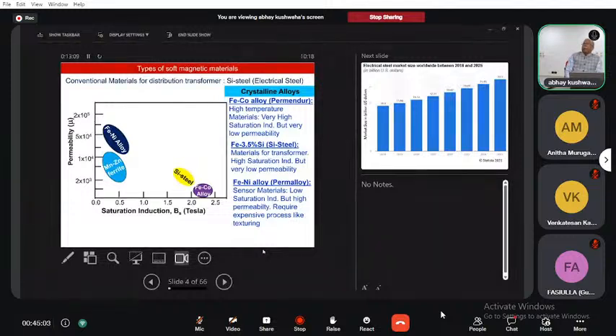But the process of making is just like a steel: melting, casting, rolling. This silicon steel is also made in the same fashion. So that is why it is called the silicon steel. And you can see in the graph where we have put saturation magnetization versus permeability. Our major goal for development of magnetic materials is how we can go higher and higher in saturation magnetization, and for the same material, how much higher we can go in permeability. So a good soft magnetic material should have a high permeability, and at the same time a higher saturation magnetization.